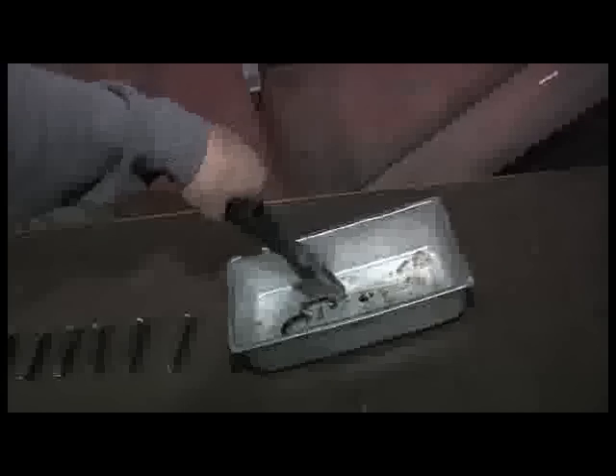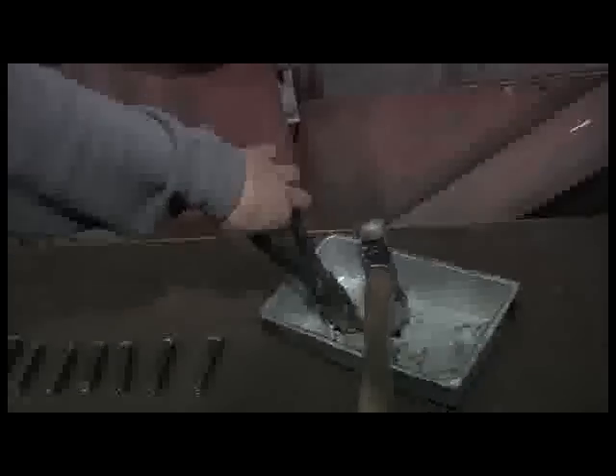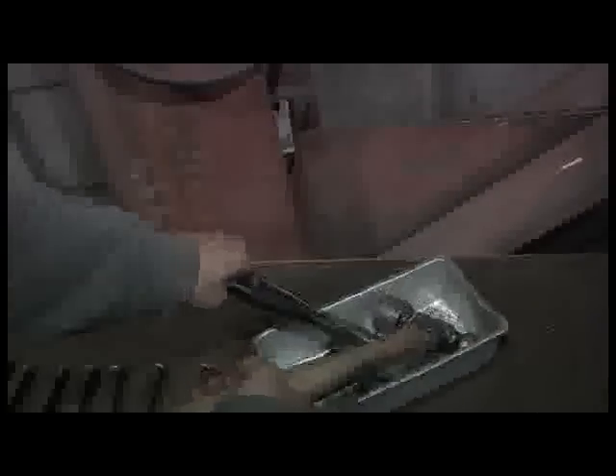The metallurgists take samples to enable the assaying lab to determine the gold content of the bars. For this purpose, they employ special vacuum flasks, which are dipped into melted gold. The lower portion of the flask being melted out, the vacuum pushes the gold up. We break the outer glass covering; by doing so, we cut off hollow parts.